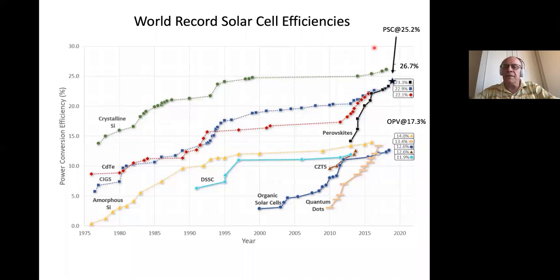So here is the development. As you see, here comes perovskite in 2012. We have initial work, and it went quickly up with different introductions of preparation procedures. And you see here a very steep slope, and today it's 25.2% efficiency for perovskite, which is higher than the other thin films like CIGS and cadmium telluride. And what is left here is monocrystalline silicon, which has a very high 26.7. And I think there's a chance that perovskite goes here, not too far away, if the coronavirus also goes away, so we can go back to the lab. I think there is a real chance.